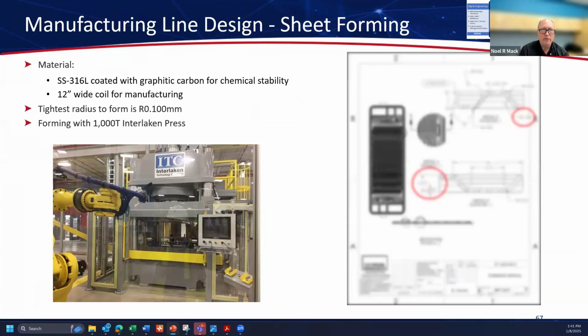Here you see a picture of the Interlaken press, and the radii are as tight as 0.1 millimeters in this case. So really important that we get the forming right to know that we have the performance characteristics that we need. So this is the 1,000-ton Interlaken press that is sitting just adjacent to the cell that you'd seen in the prior slide. The graphic on the right has been shaded out so that the sensitive information is removed, but essentially what would be hidden behind those two red circles are some of the tight tolerances that we need to hold through this process.